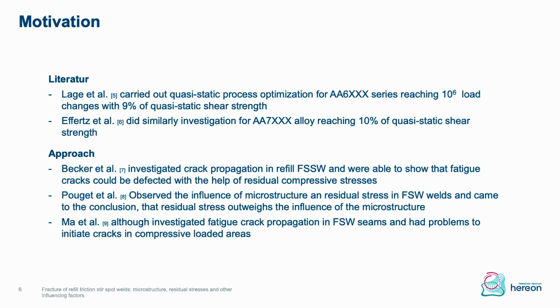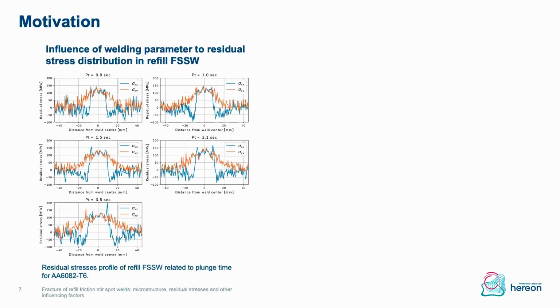And Ma et al. also investigated the fatigue cracks in friction stir welds and even had problems to initiate fatigue cracks in compression loaded areas. So my first approach was to influence the residual stress distribution by influencing the welding parameters, as you see on the left-hand side. Here we changed the plunging time, so also the total welding time, but only saw that we could affect the range of the residual stress affected area, but not the absolute height of the residual stress.